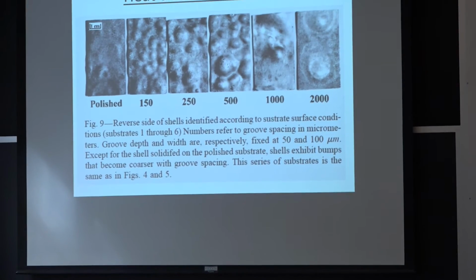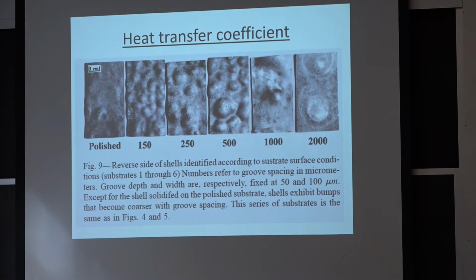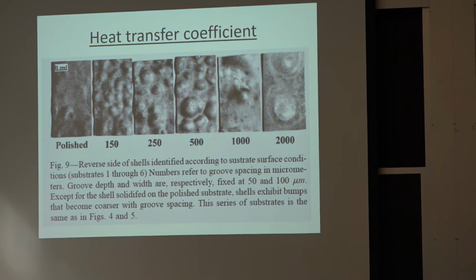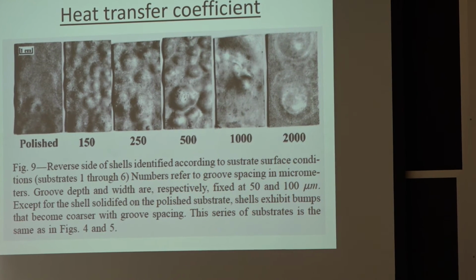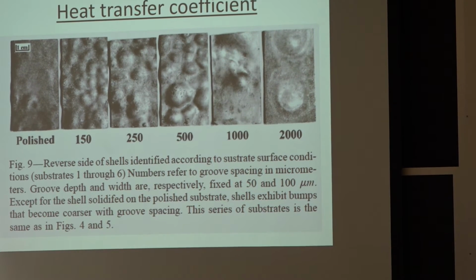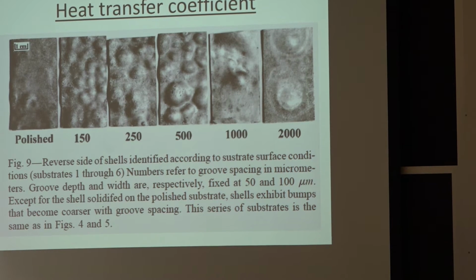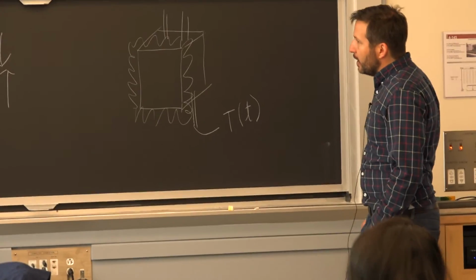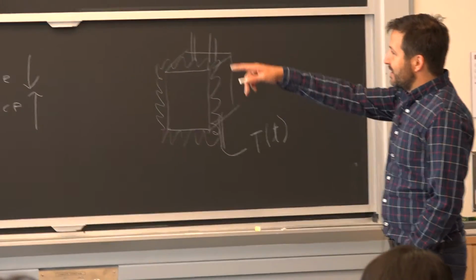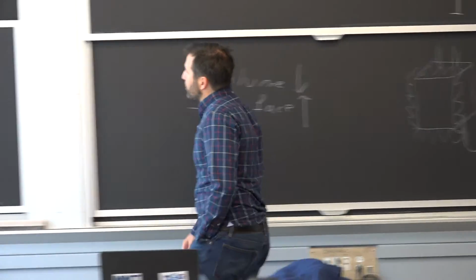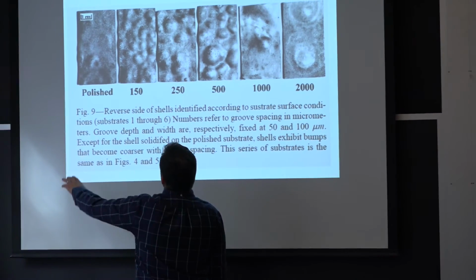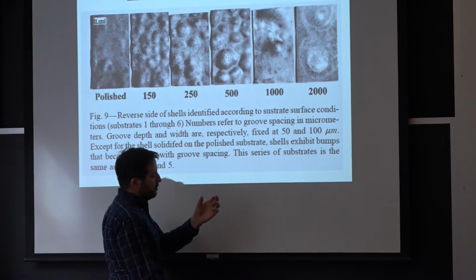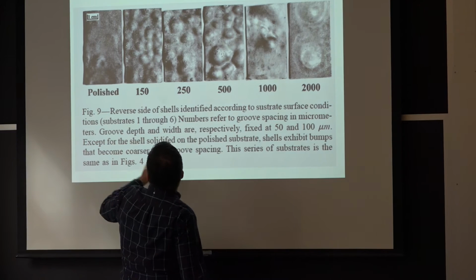So we're looking here at the strip of copper, and I'm sorry I couldn't keep any of them. The piece of copper that built over this substrate or mold surface or roller surface, for the analogy to the strip caster. And you can probably see these little deposits or castings have a different surface morphology. So we're looking at about 2-3 inches in size. So this one here has maybe like 5 bumps.